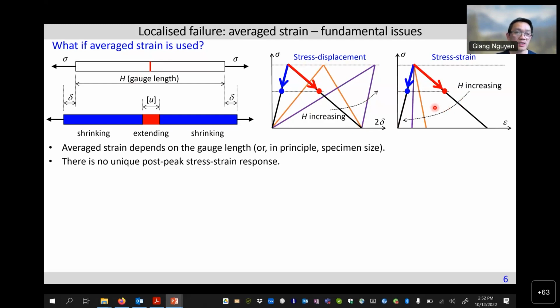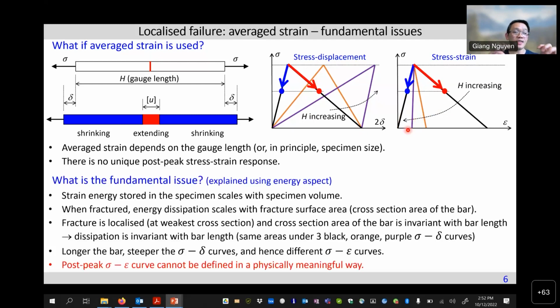So in this case, the answer here is that it's incorrect if we do the averaging the normal way, like an engineer usually does. Okay, because there's no unique stress strain here that we can use. The fundamental behind this, I try to explain using the energy principle. Like you have a spring, you load the spring, so the longer the spring, the more strain energy you have. But in the end, the spring will break at one specific point, regardless of how long it is. So all the energy stored in the spring will be dissipated, will be released at one specific point. And regardless of how long your spring is, it will break at one specific point, and it is releasing the same amount of energy.